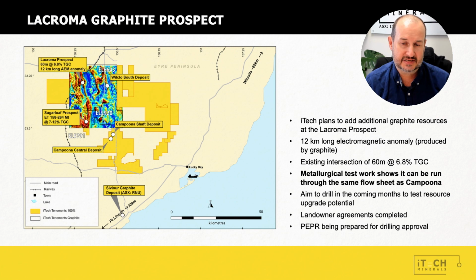So at Lacroma, there's an existing drill hole intersection of 60 metres at 6.8% total graphitic carbon. So we know that that anomaly is caused by graphite subsurface. What's also important is that metallurgical test work has already been undertaken on that drill hole, and that shows that it is amenable to the same flow sheet that produces the black graphite that comes out of Campoona.